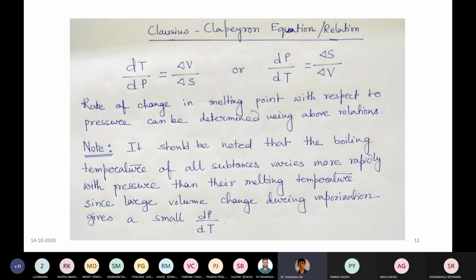So what does it mean? The rate of change in melting point with respect to pressure can be determined using the above relationship. From there you can understand the rate of change in melting point with respect to a defined pressure. And this is a very significant concept, at least for secondary steel making operations, because of pressure, the vacuum steel making technology or ladle metallurgy, the application of vacuum is very important. The minimum vacuum level is a very important part in order to refine the steel in the secondary steel making shop. And there this equation is very important, because there the concept of rate of change in melting point and all those things, how the dissolution of gases inside the liquid steel, you have to take care of. Those things are very important. So the Clausius-Clapeyron equations are very significant in understanding such processes, at least in the case of secondary steel making.